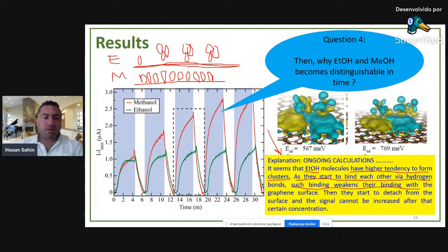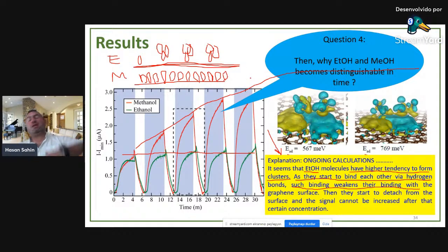So this is why, in the beginning, ethanol results in some increase in the base current, but in time you cannot obtain more and more increase because of this cluster formation. But with methanol, you can add more and more. Of course, we expect that after a certain value it will saturate again because you will cover all the surface with methanol molecules. Then you cannot dope the surface anymore.